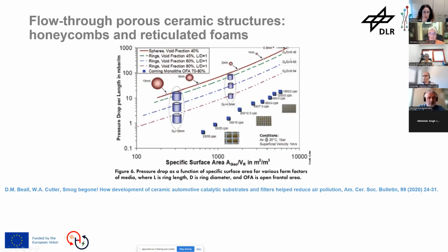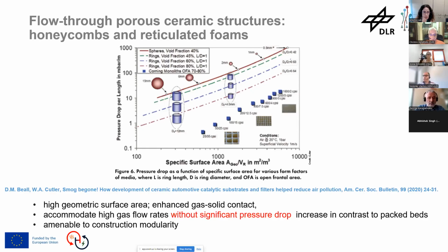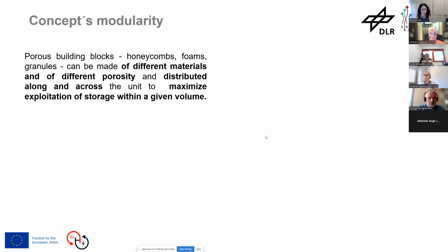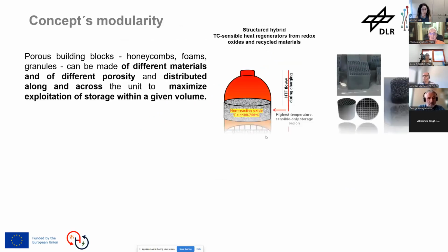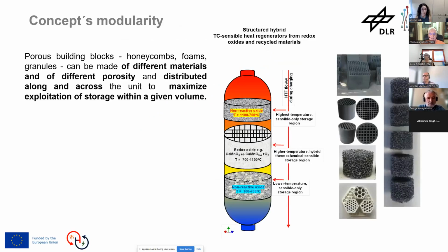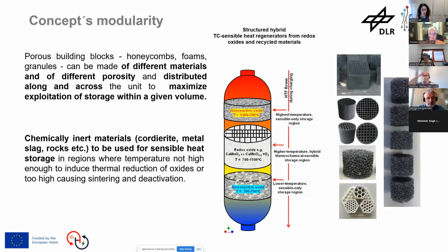So we go in for high-throughput flow-through porous structures like honeycombs and foams, which have these significant advantages, especially very low pressure drop. And also they are amenable to modularity, meaning that one can build a unit from several small pieces of the same base unit, and also fine-tune this unit in a cascaded way along the length by using different redox materials along the length of the bed, and also sensible-only materials in higher or lower temperatures when these oxides do not operate.